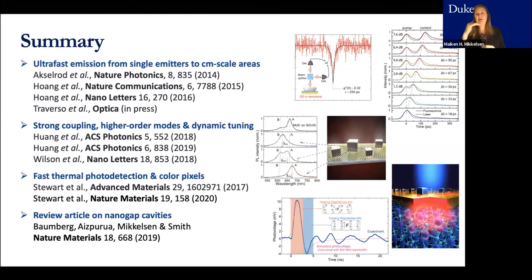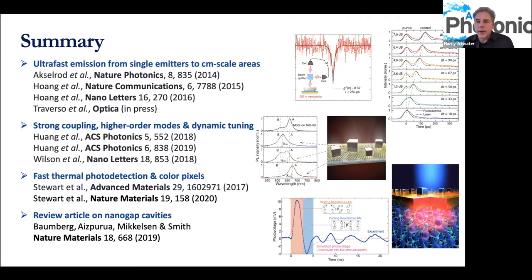It also does have some in-plane fields. First, we thought we wouldn't really see much enhancement from the 2D materials, but when we did the calculations, we could see the cubes had rounded corners, and we actually do have some not negligible enhancement in the in-plane direction, so that's useful as well. Otherwise, this is really just a general way of thinking about nano gaps, structures, and large field enhancements, but there's a wide range of ways that you can design other plasmonic geometries, right? If you have some specific structure or material you're interested in enhancing and modifying, you can think about how we want to make large field enhancements so that it's coupling preferentially to that structure. Okay, yeah, good, great.